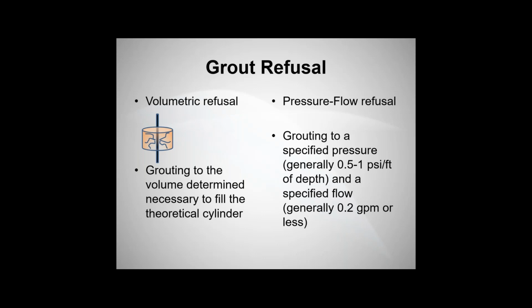The reason is that often you can push grout further than you can control the spread of that grout. And as we said earlier in some of those slides, you don't want to have an uncontrolled spread of grout. So that calculation of how much grout goes in the soil goes into your volumetric refusal. Basically, you take your theoretical cylinder, which is based off of the amount you figured you need to inject. That's going to be a volumetric refusal, and if you get to that point, you're going to stop grouting and move on to the next stage.